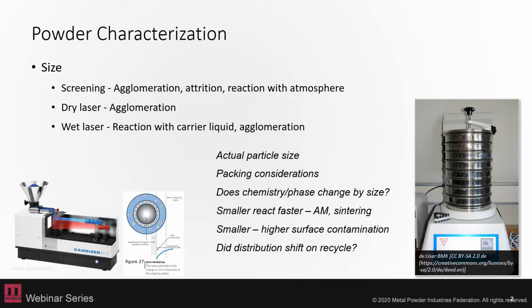So there's your typical stack of screens, size classification to give you a bell curve shape, but you can also use a laser system such as the CamSizer shown down here that will give you your size distribution as it's looking at the cross section and shadow images of those features of the powders on a detector to give you a size. But again, your dry laser or your wet laser system might not pick up agglomeration of those powders. Those systems are typically assuming a spherical powder. So any off shape features that you have will not be identified necessarily.